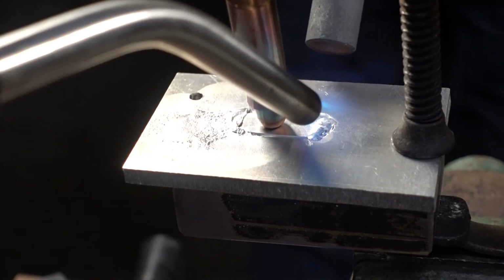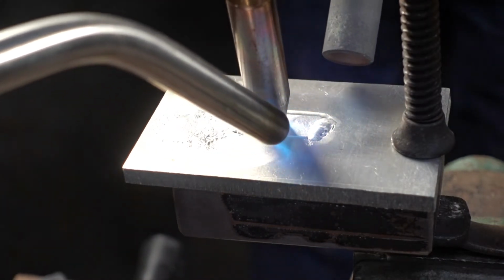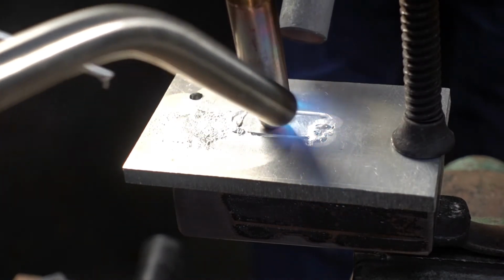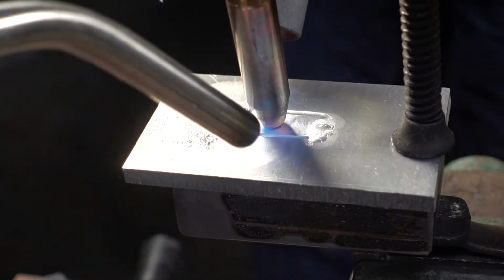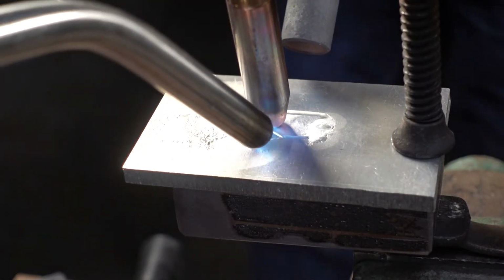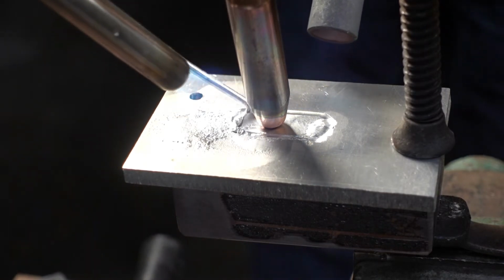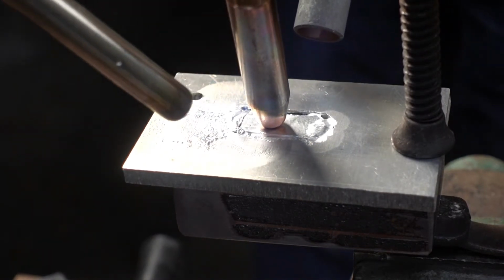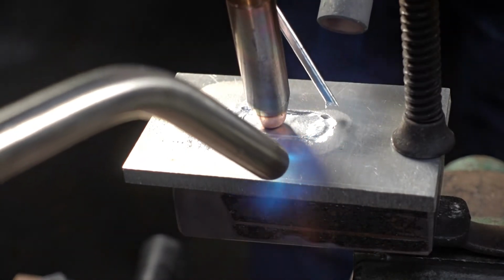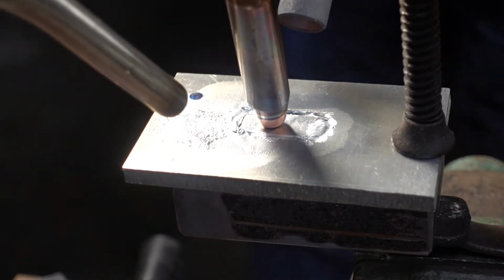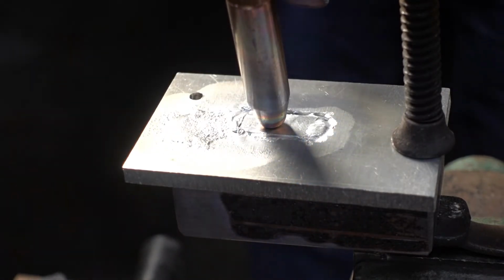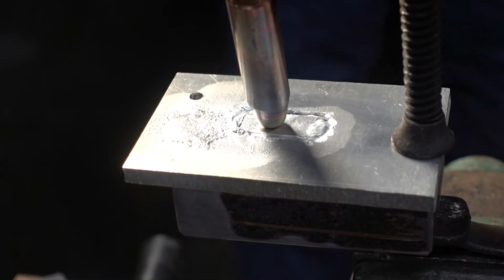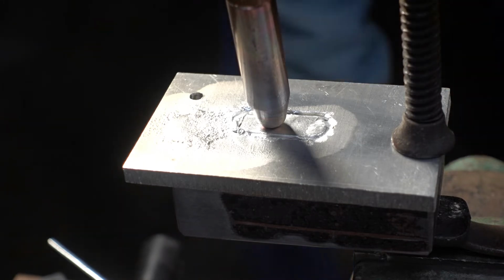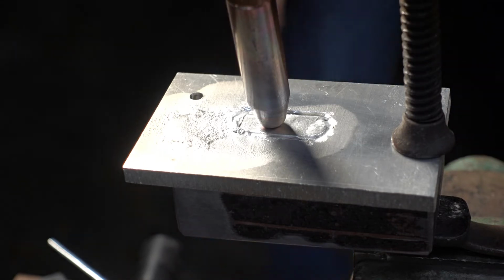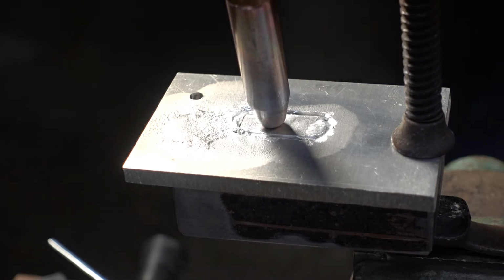So you want to just do it locally there. Let it go down into the crack. Just run it all the way through. Okay. That took a long time to heat up. It could be because of the 1/4 inch thickness of the plate, and also the copper backing.